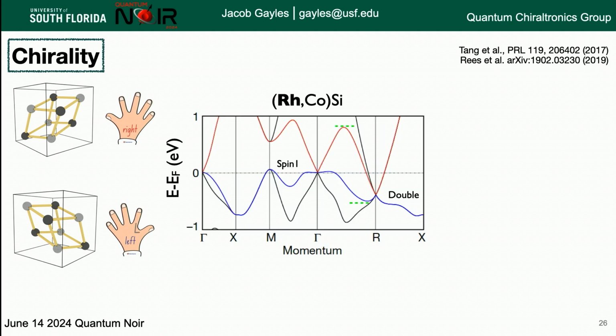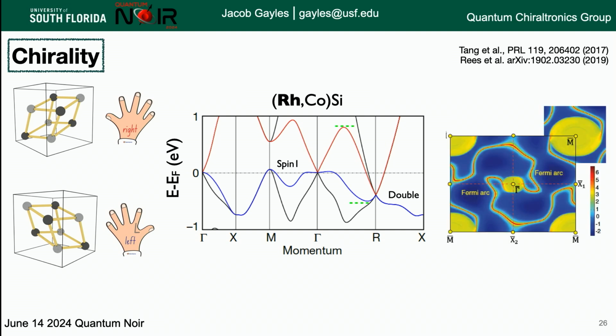And so this is the band structure for this material, depending on which compound you're looking at. You have, without spin-orbit coupling, the spin 1, and then you have this double fermion that I showed you earlier. And then, like I said earlier, it's what's in between that counts. These are the Fermi arcs, or the in-between stuff that we're interested in. That's what causes the spin current and can be used to manipulate skyrmions.